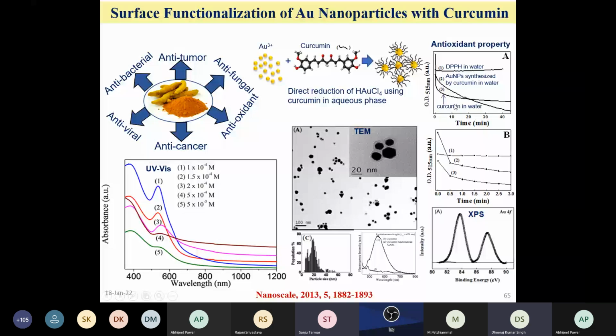So now when we mix this curcumin gold nanoparticle in this DPPH, you can see that this absorption peak intensity is reduced at 515 nanometer. So this DPPH radical test shows that in the presence of curcumin, in the presence of gold nanoparticle, it's showing enhanced antioxidant property, which can be very helpful in understanding how to kill the cancerous cell also. So after understanding this, many biological people using the gold nanoparticle have utilized this concept, and they have published a lot of research work to kill the cancerous cell using curcumin in the presence of gold nanoparticle, and they have applied it in mouse and something like that.